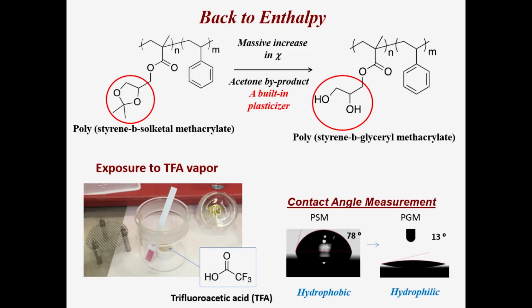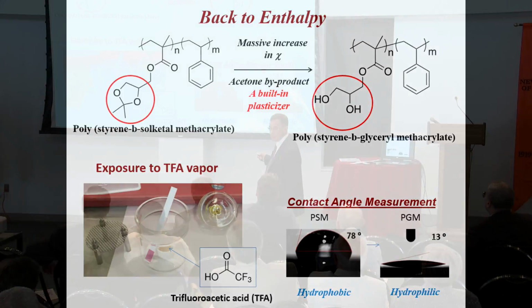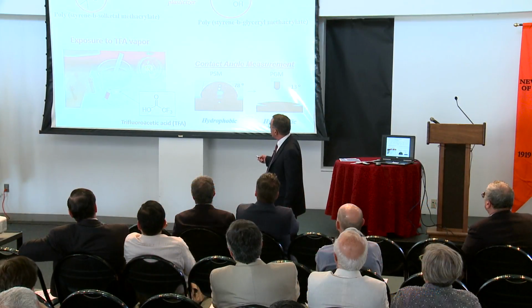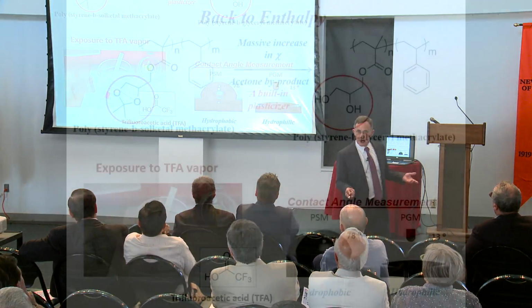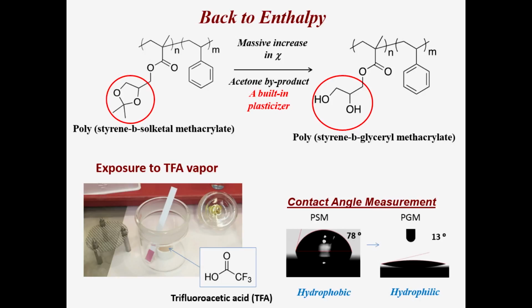And the magic that you do is that initially I'm going to start off with a copolymer that's hydrophobic. I'm going to start off with polystyrene, which is this, and this block here, which is called a polysulketyl methacrylate. Hydrophobic, soluble in nice organic solvents. Spin coat films very nicely. I can spin coat films down to a nanometer or less.